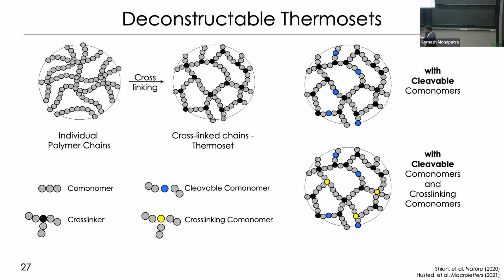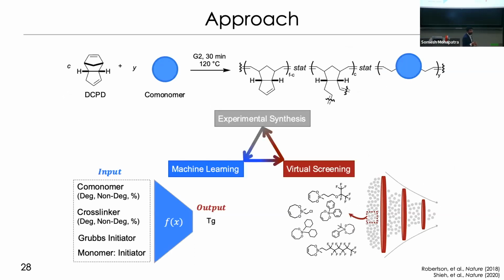What started as a very good-natured and innovative approach of increasing recyclability unfortunately took a hit when it came to glass transition temperature. It decreased the maximum temperature at which these polymer end products could be used. So the challenge was tackled in another framework, which started with the experimental synthesis, with the base as dicyclopentadiene or DCPD, including this cleavable comonomer in a standardized experimental process, and getting this entire data set, which was then handled through some pretty interesting and innovative machine learning approaches.